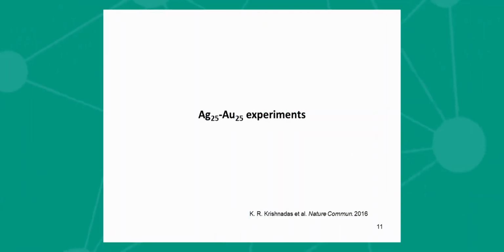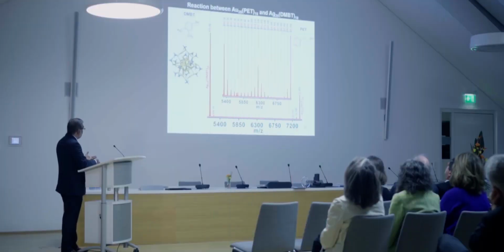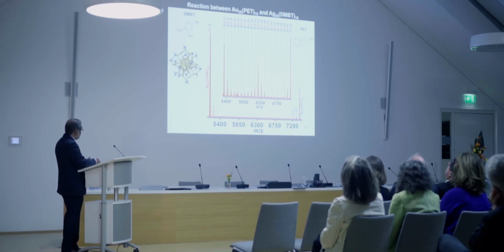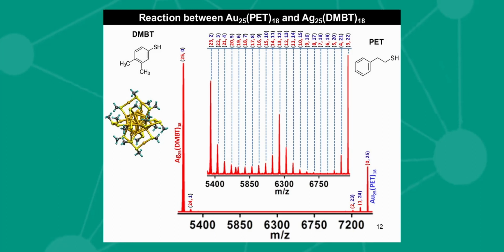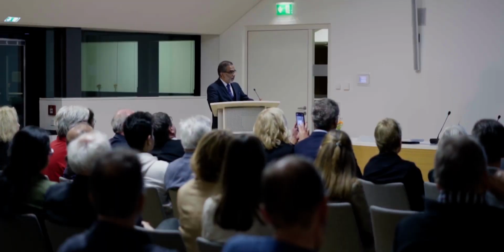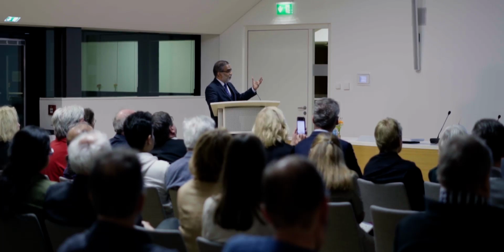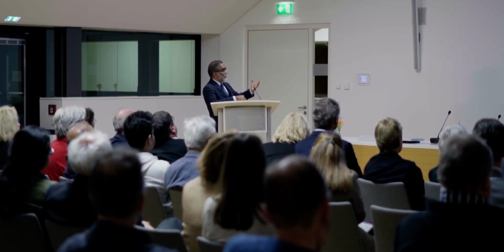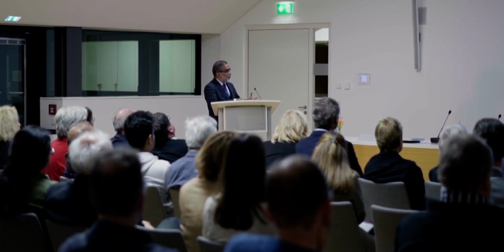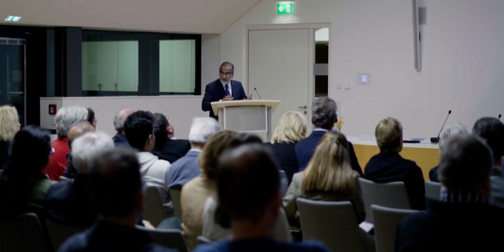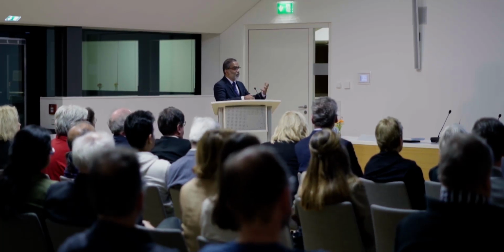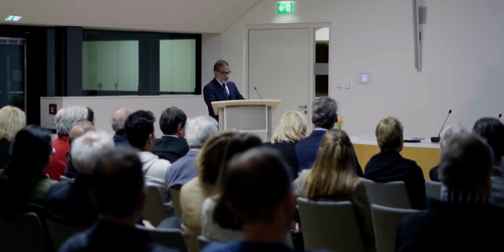So I can do this experiment with that cluster and that cluster, again protected with ligands, and we saw that a cluster of that kind is reacting with a cluster of this kind. Here I label this cluster as 0, 25 to indicate that there is no silver in it, and to indicate that there is no gold in it, I write it as 25, 0. This is what I have to begin with. The moment I mix, suddenly some new peaks come up for the reasons I told you. And these, if I expand it, I see many peaks like that. They are all atom exchanges, but there is a peak here which is of greater intensity. Today we understand that this is because of greater entropic contribution to the total free energy of the system.